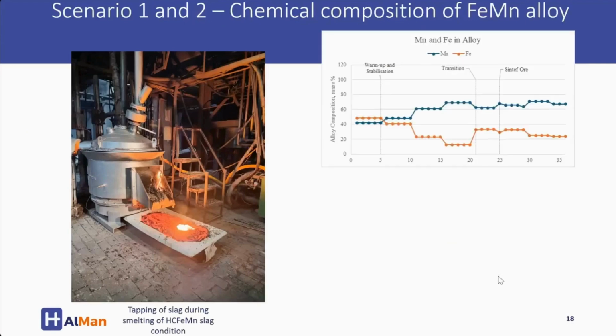Now I'll give you the chemical composition of the alloy that we tapped during the campaign. From tap 1 to tap 20, this was during the time when we were smelting slag. One thing you'll notice is the manganese was increasing with every tap. This is because we started off with an alloy as the starting metal heel that didn't have a high alloy content, high manganese content, which distorted the initial manganese concentration. But at the end of the batch, we managed to get like 70%; our target was to get like 75%.